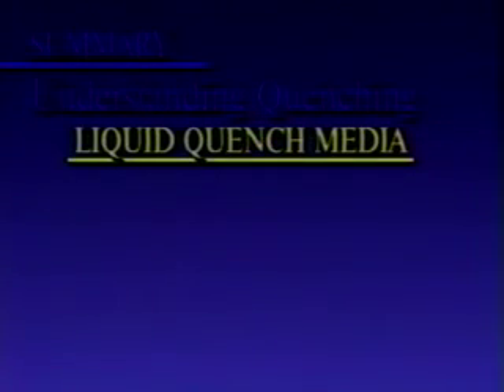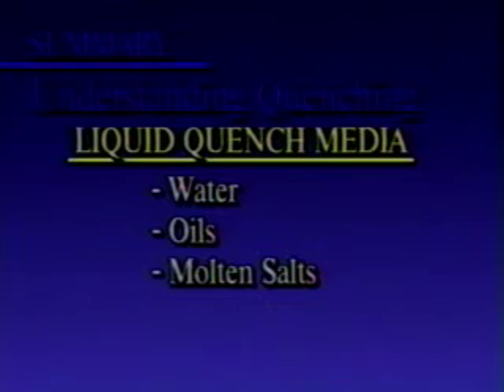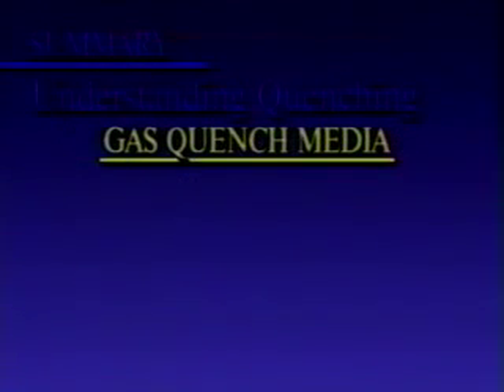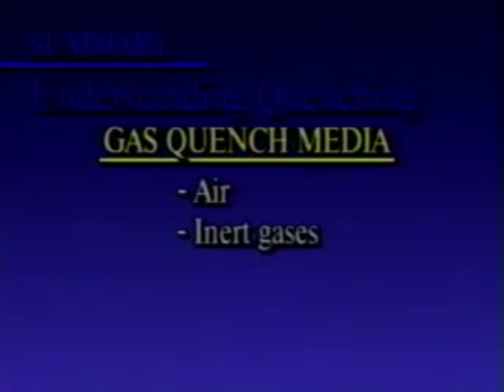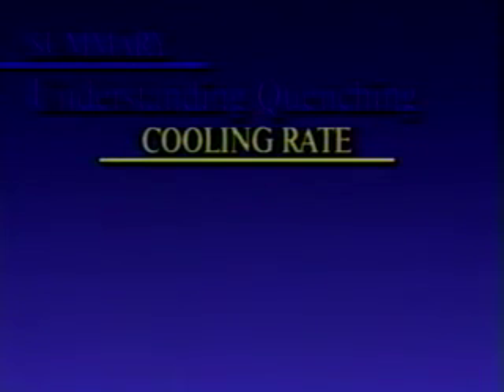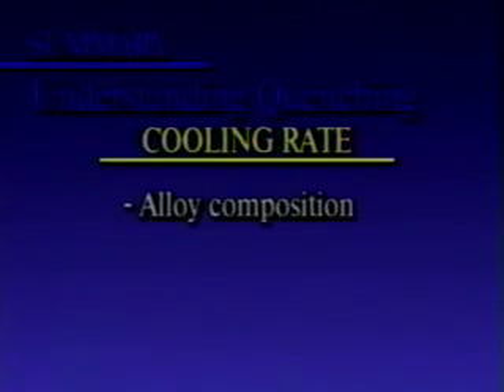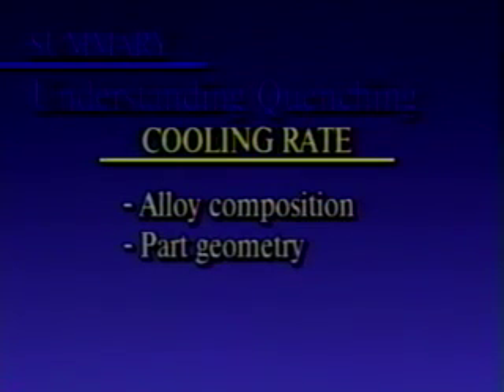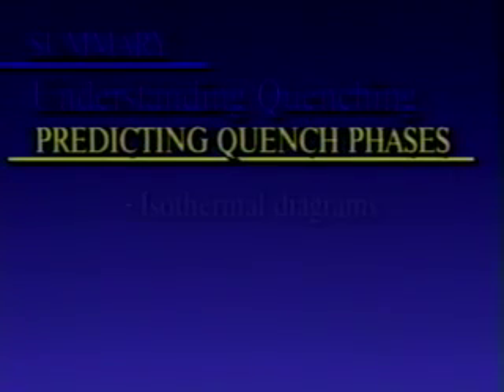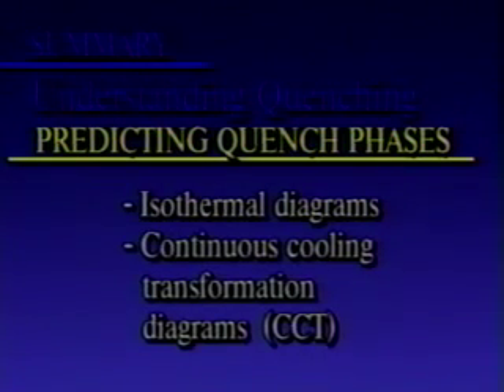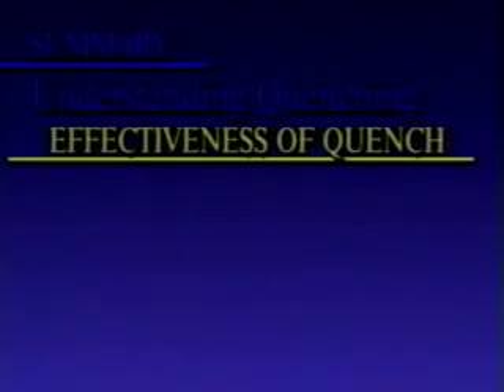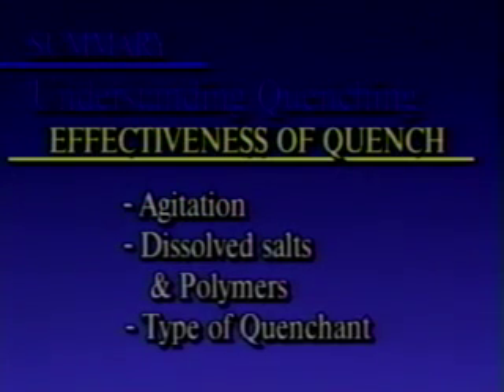There are 4 basic types of liquid quench media: water and water-based solutions, oils, molten salts, and molten metals. Several types of gas can be used for quenching: air and inert gases. The proper cooling rate assures cooling evenly without distortion or cracking. Cooling rate of a quenchant depends on the alloy composition of the parts, the geometry of the parts, and the size of the load. Predicting the phases that form during quenching is done with isothermal diagrams and continuous cooling transformation diagrams. Effectiveness of the quench depends on agitation of the quench, the dissolved salts and polymers, and the type of quenchant, liquid or gas.